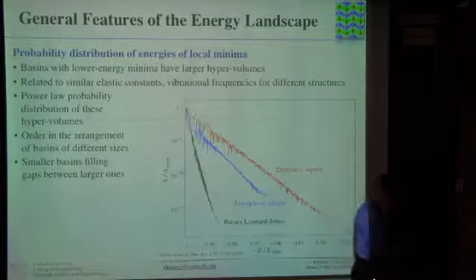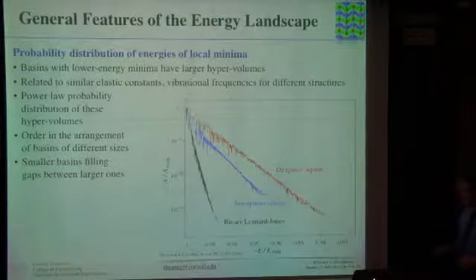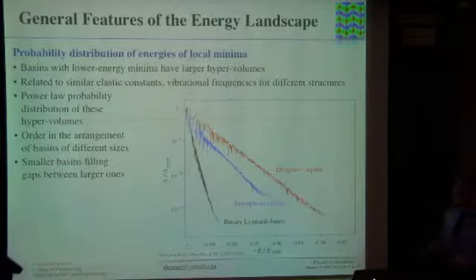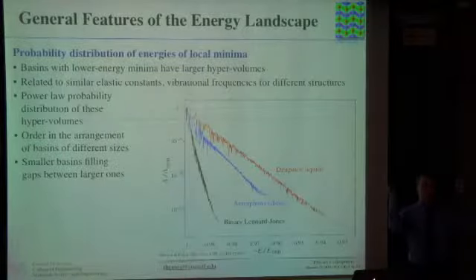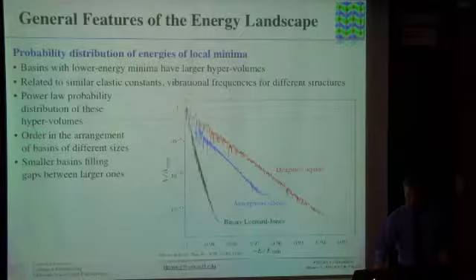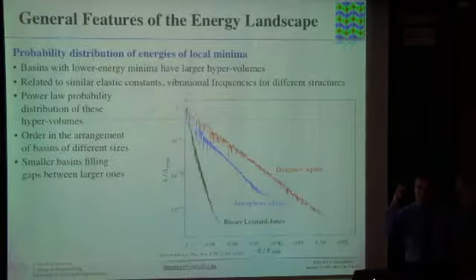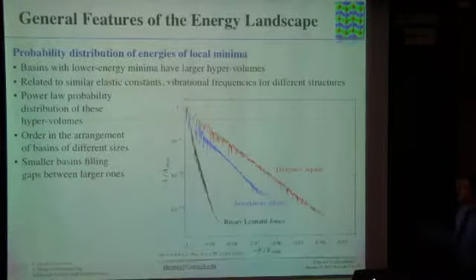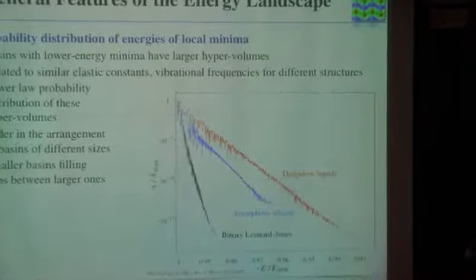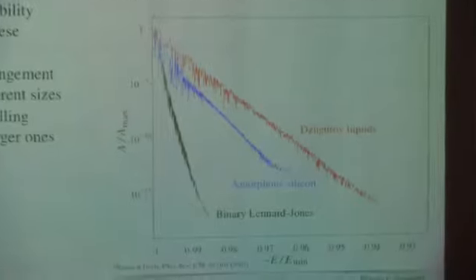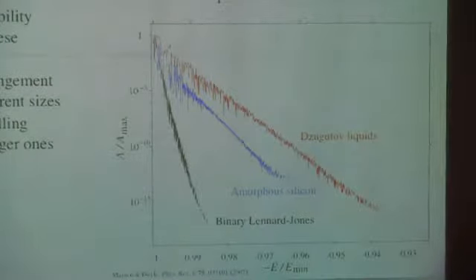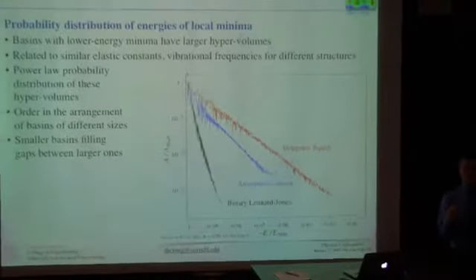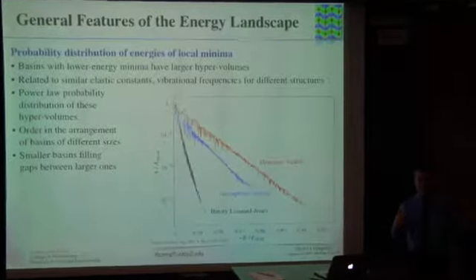The other observation about energy landscapes, shown here in a paper by Massen and Doye, is that when you look at these minima, and you look at the region of attraction, the size of those basins, there's actually a distribution. The deeper the minimum is, the larger, on average, that basin of attraction you would have to fall into that minimum. And the reason for that is actually quite straightforward. If you look across all kinds of materials, the kind of bonding you have, ranging from very soft van der Waals bonding to more strong chemical, covalent, ionic, and metallic bonding, if you look at how the energy changes as a function of change in bond lengths, it's actually not that dramatically different across materials. It might change by maybe a factor 10 or 100 from material to material, but it doesn't span more orders of magnitude than that.